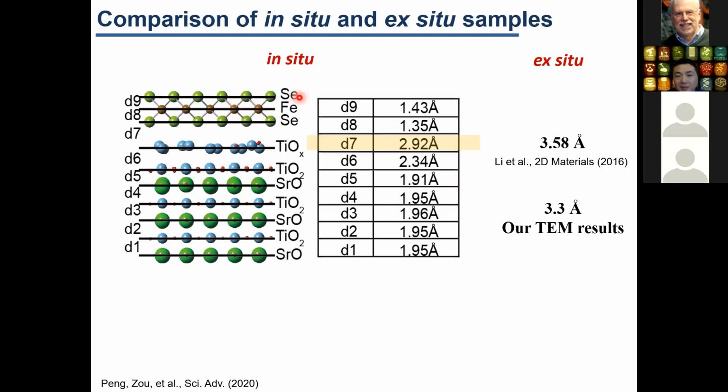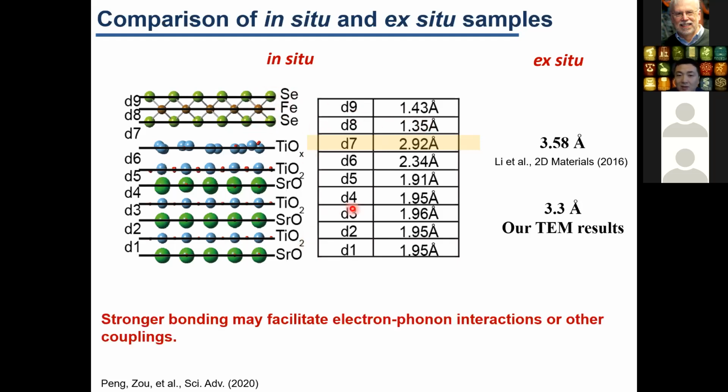When we make this monolayer iron selenide, the inversion symmetry is gone, and the material itself doesn't look like the layers in the bulk. So this may also contribute to the enhanced TC of this monolayer iron selenide. But so far we haven't reached any conclusion yet. We are trying to do calculations to show what exactly this change of distance will do to the material itself.